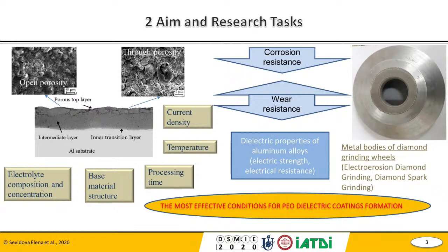It's also well known that porosity is one of the most important indicators of resistance of each material, and especially for our PEO coatings. And the biggest negative effect can be seen in corrosion resistance. And we can see that through porosity makes the corrosion resistance decrease. And in general, it's also well known that through porosity also reduces wear resistance of coatings.